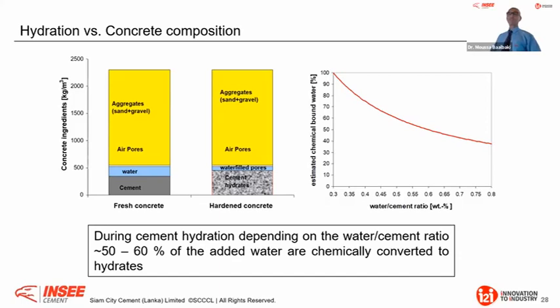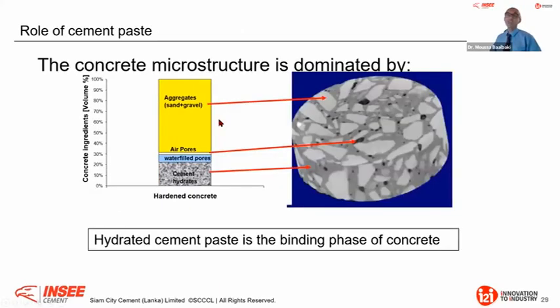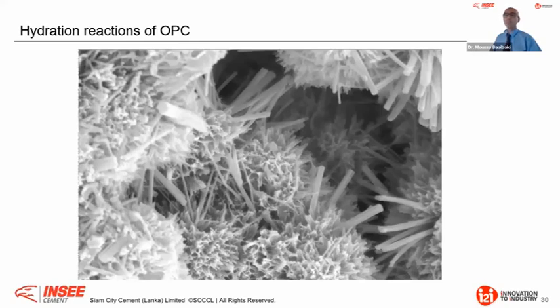Therefore, that is why at the end of the day, when you look at the microstructure of such a concrete, it will be very different, not because your OPC has somehow developed a different product. No, you always develop the same product. You develop calcium silicate hydrate, you develop calcium hydroxide, you develop trisulfoaluminate, monosulfoaluminate, but the difference is in terms of porosity, depending on water-cement ratio, depending on compaction, depending on other parameters that I will come to in a couple of segments. This is a scanning microscope image of a cement hydrate paste. Therefore, you see that even if we fully hydrate our cement paste, we still have a lot of porosity. That is the question here.